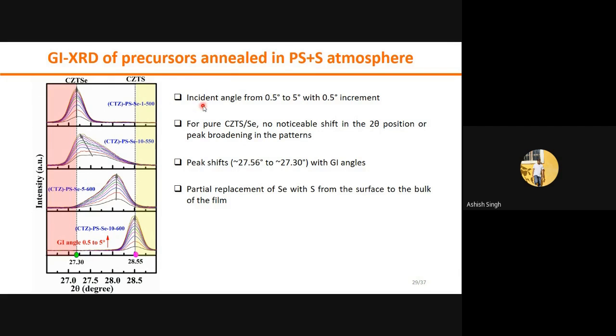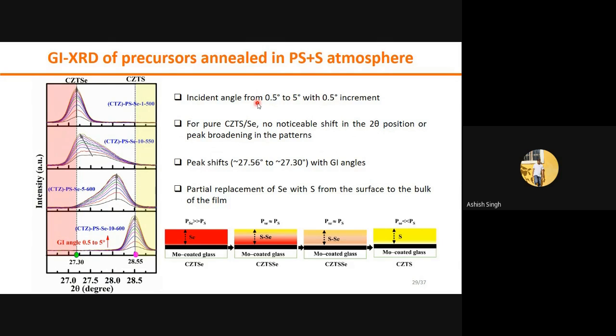For that, we did grazing incidence X-ray diffraction at different incidence angles. The incidence angle was taken from 0.5 to 5 degrees with an increment of 0.5 degree. That means if we use a 0.5 degree incidence angle, the XRD will give surface information. If we increase the incidence angle, it will give the bottom information.